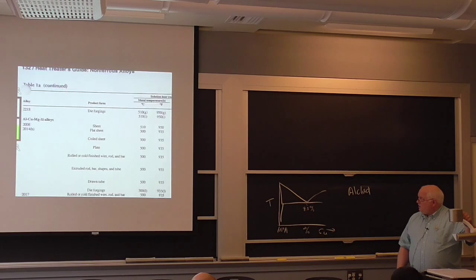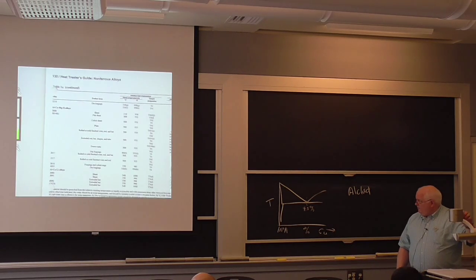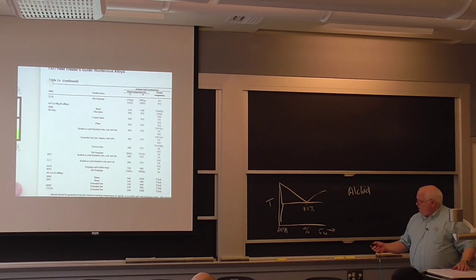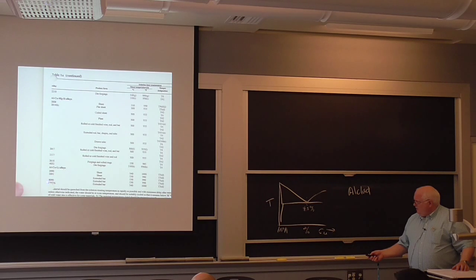So here's the heat treater's guide for aluminum alloys, and we have these 2000 series alloys, aluminum copper with a little magnesium or silicon, and you get precipitation hardening. Aluminum copper lithium alloys. Here's an 8000 series extruded bar.